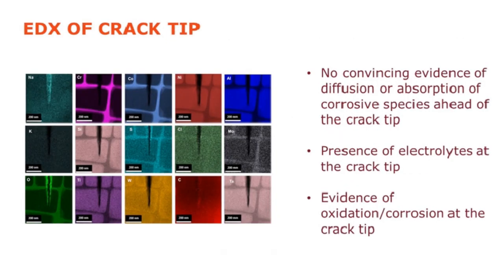So some EDX then, just to look at what's going on at the crack tip here. And again, I've just taken a little snapshot. I've looked at quite a few of these. But what we can see is, firstly, there's no convincing evidence of diffusion or absorption of corrosive species ahead of the crack tip. It all appears to be happening at the crack tip. There's not much going into the material. Certainly not a lot of evidence I've seen of that. We do see presence of electrolytes at the crack tip.